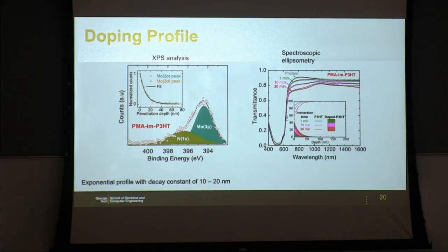So not only does the film get efficiently doped, but the dopant happens only over a thickness of 10 to 20 nanometers, which in our devices would be kind of the typical thickness of a layer. So if you wanted to produce a separate hole collection layer in this case, because we want a high work function electrode, you would have to deposit, for instance, a layer of molybdenum oxide that has that 10, 20 nanometer thickness. Here, through that simple dipping and diffusion process, you get to the same results.